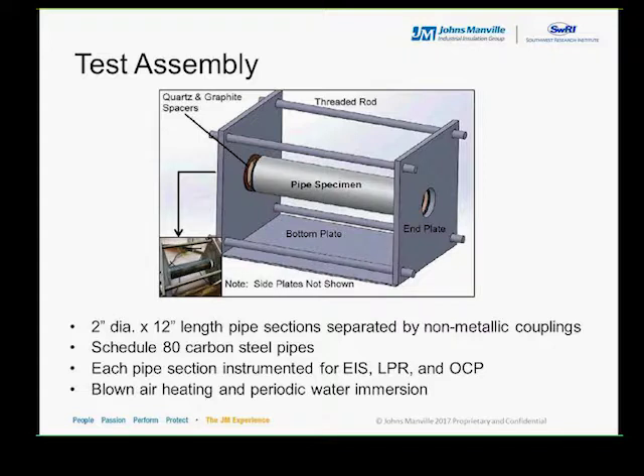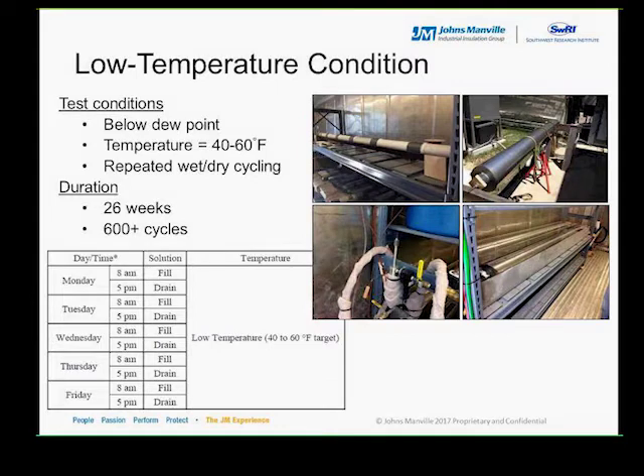Low temperature condition. For the low temperature condition, inline pipe spools interconnected with isolation couplings are used. The couplings are used to electrically isolate each of the pipe spools with the purpose of executing the electrochemical measurements. The gap between the couplings and the pipe surface are sealed with silicone to prevent water ingress inside the pipe. Then the pipe spools are insulated with a given thermal insulation wrapped with a metal sheeting following field insulation practices.